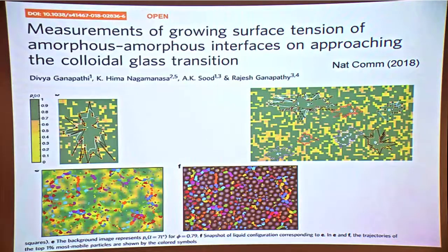And what we have shown here is that we have superimposed that wherever this interface is, that's where the most mobile particles are, or CRR as they call. So all the mobility in the glass is occurring at the interface of this amorphous interface. And the conjecture is that the mobile particles, irreversible events, are really related to this amorphous interface, which is what you would expect in a polycrystalline material, but which now we show you can define with some persistence function, this idea of an amorphous interface.